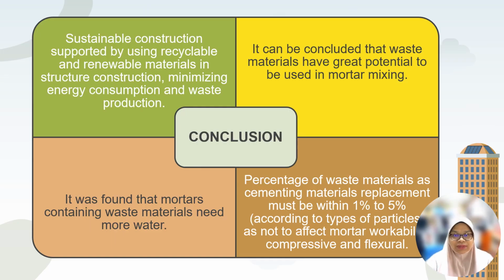It can be concluded that waste materials have great potential to be used in mortar mixing. Though it was found that mortar containing waste materials needs more water to reach the same level of workability as conventional mortar, waste materials can still be used if the mixing ratio is correct. It should be noted that the percentage of waste materials as cementing material replacements must be within 1% to 5% only, according to type of particles, so as not to affect mortar workability, compressive strength, and flexural strength.